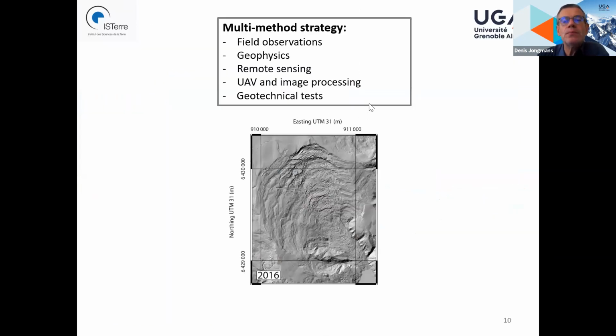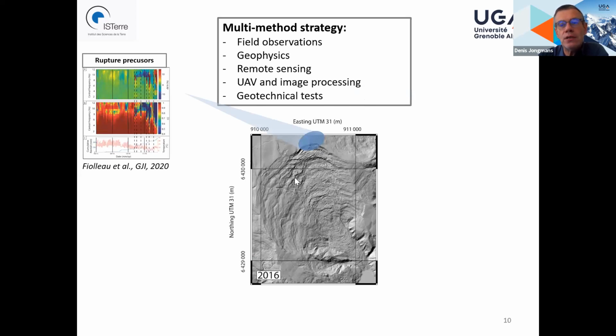So what we try to do is a multi-method investigation of this landslide, combining field observation, geophysics, remote sensing, UAV and image processing, and geotechnical tests. Very briefly, we studied the seismic rupture precursors at the headscarp, instrumenting a block before it slid, and showing with seismic noise that it was possible to obtain some precursory patterns on parameters like the variation in velocity or the correlation coefficient using the correlation technique, and also on the number of events or the resonance frequency. It was a paper published in 2020.